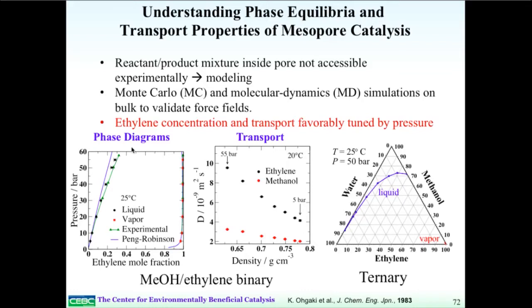usual chemical engineering programs. We can also look at the transport properties, and you can tune the transport of ethylene in this liquid phase quite dramatically simply by increasing the pressure. As you go up to 55 bar, you've essentially increased the diffusion constant of ethylene inside the system by over a factor of 2. We can also look at what happens when you start adding water. We can look at the solubility of ethylene in the system. These are often things which these Peng-Robinson type equation of state models don't do too well.